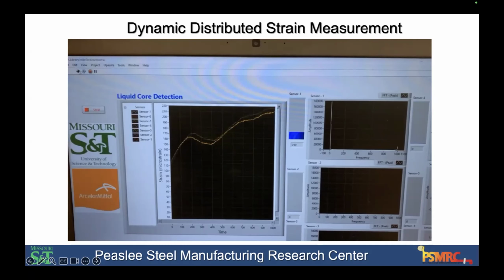But unlike using traditional strain gauges where you have to supply power at each point and you have to have individual signals back from each strain gauge, we use a single fiber and we place two FBGs on the fiber on each beam and then string them together and multiplex them for a single fiber signal, a very low cost instrumentation environment for detecting liquid core. And that's really important if you're running casters where you want to control dynamic soft reduction, improve centerline segregation and the like.